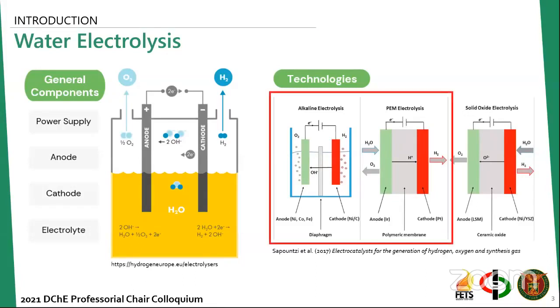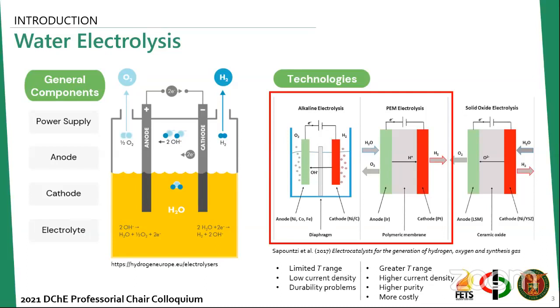So we will be focusing on these two, since we know that in normal conditions, water is in the liquid phase. Comparing the two electrolyzers, the issues that arise on alkaline water electrolyzers are the limited temperature range, low current densities leading to corrosion, and durability problems. For the case of PEM, or the proton exchange membrane, while it operates at a higher current density, a greater temperature operating range, and a higher purity, they are more costly due to the titanium-based contact elements.